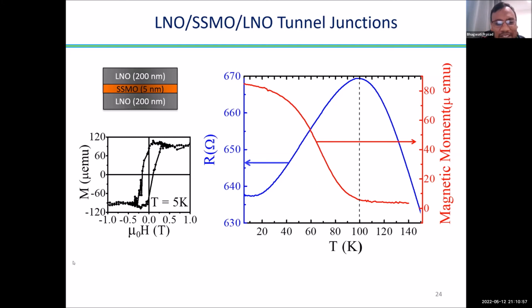Yeah, very good question. I like this really. Nobody has asked this question before. I mean, you pointed out a very right thing here. So what happened is that when you measure the film magnetic properties, like a 5 mm by 5 mm sample, so uniform films. But when you measure the R versus T of the device, what you do is that you basically fabricate it, you make small nano pillars and so on. So with that, you change the magnetic property as well. You change the magnetic dimensions, so the demagnetization and shape anisotropy will play a role. And then you see that the TC doesn't match.